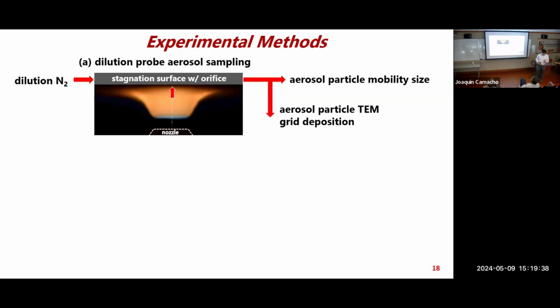In terms of sampling this plane, we have a stagnation plate where this flow is impinging as a counterflow at the stagnation flow. We can have a sampling orifice in there where we can dilute and pull some of this flame gas out. What I've done is feed it into this aerosol analyzer to get a size distribution. But also downstream, it's a diluted aerosol, and I also use this to deposit onto a TEM grid to get a sample under the microscope of the structure as an aerosol, depositing onto this grid diluted downstream. So that's one measurement I'll present.